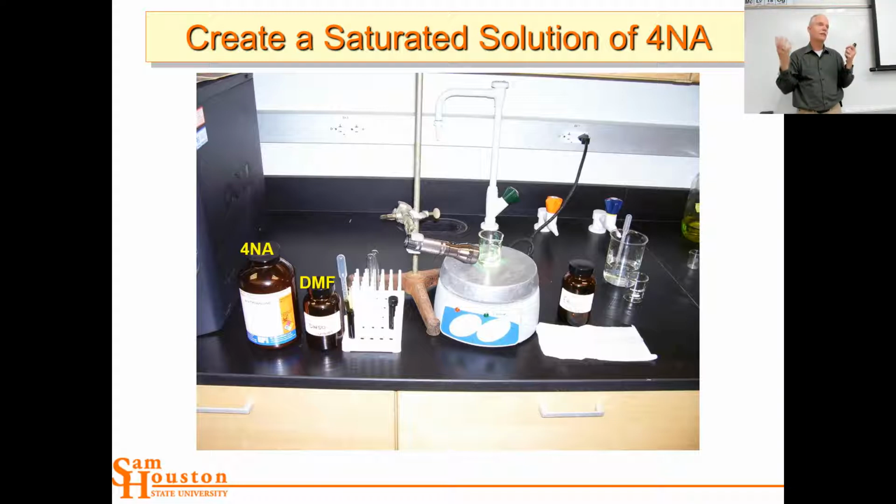and you don't see it. But if you start to see microcrystals, you'll see little sparks. You'll see the laser get flashed into your eye just a little bit. You'll see little red flashes from the laser. And it's a way to tell if you're starting to see precipitation. That scattered light from particles is the Tyndall effect. So you can use the Tyndall effect to tell when precipitation is beginning.